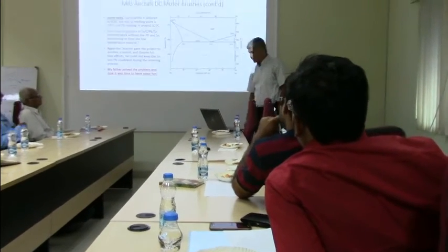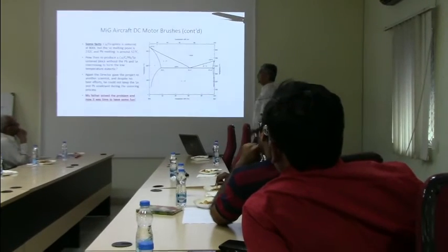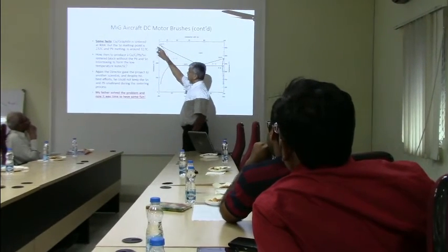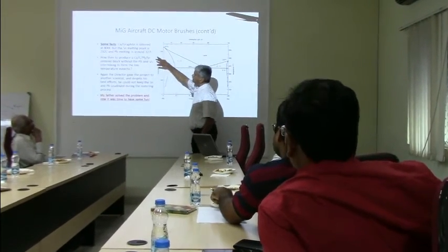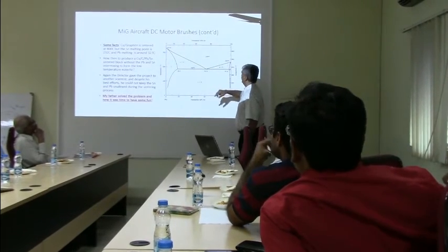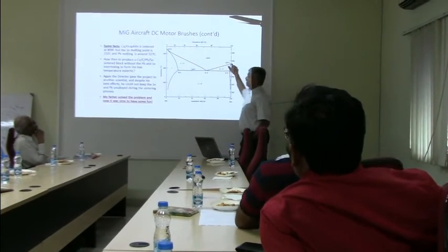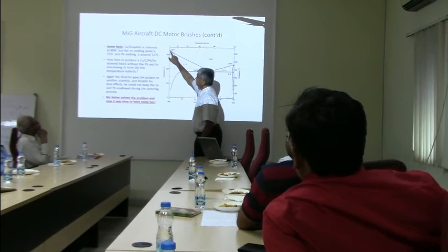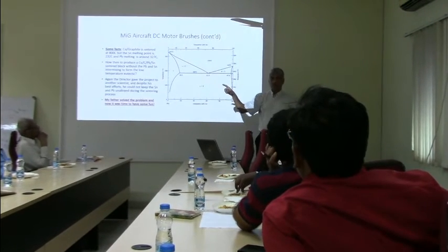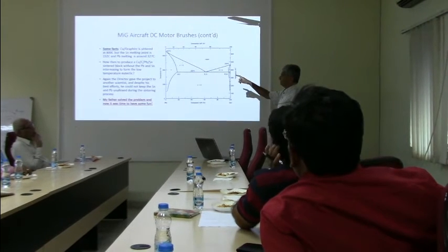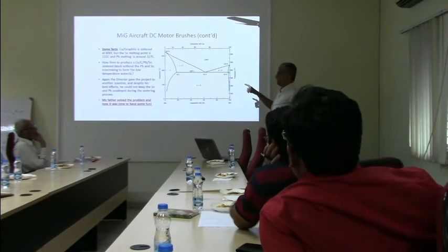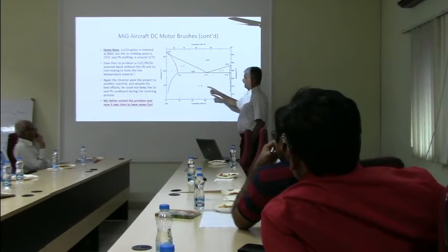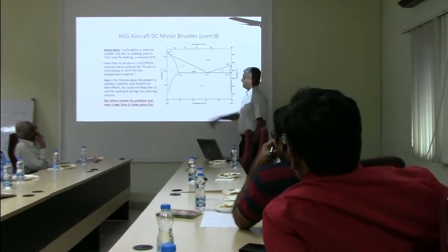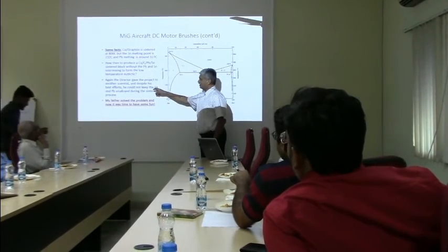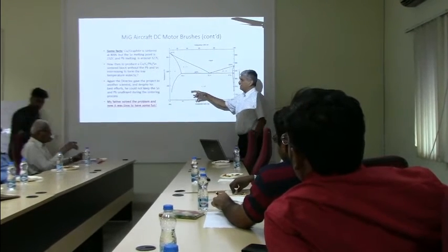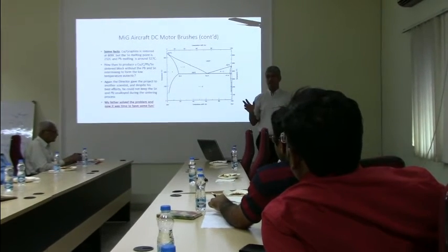Now technically this is a huge challenge because if you think about it, copper and graphite is typically sintered at 800 degrees Celsius, but the tin melting point is 232 degrees Celsius. Lead melting point is 327. So putting all these dissimilar materials together and preventing the lead tin from forming an alloy is a very difficult task. And again, same story. Another scientist took this up, and despite his best efforts, he could not keep the lead and tin unalloyed during the sintering process.